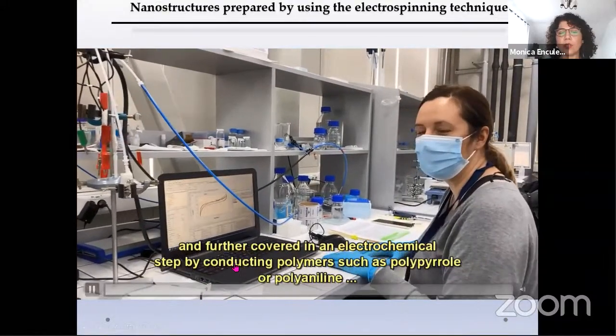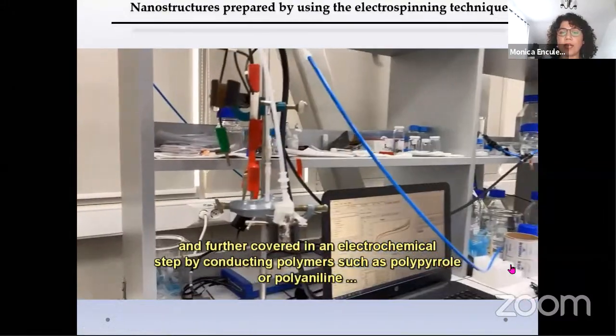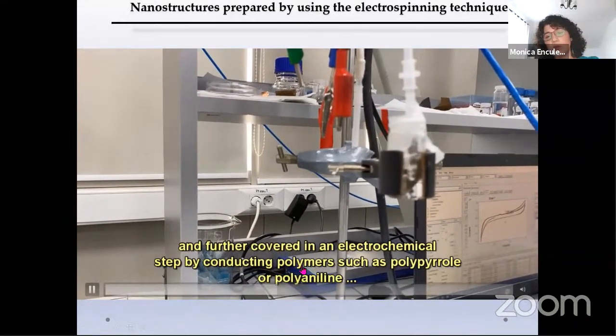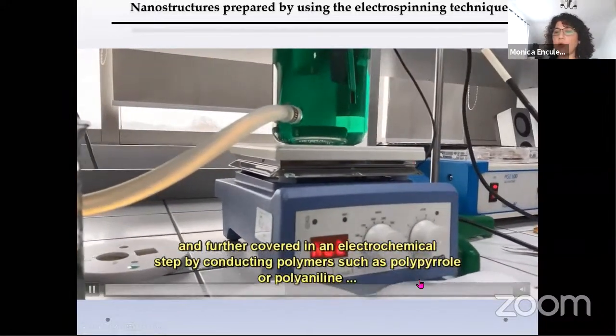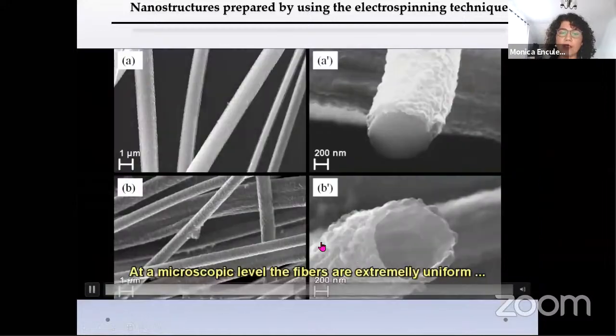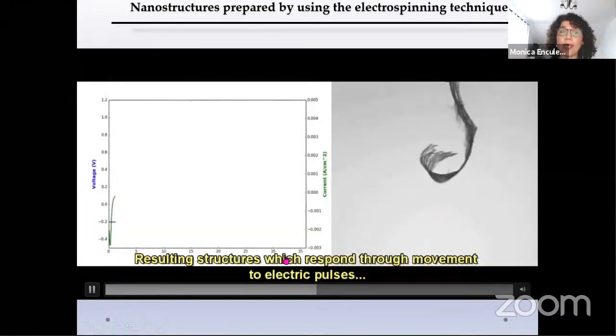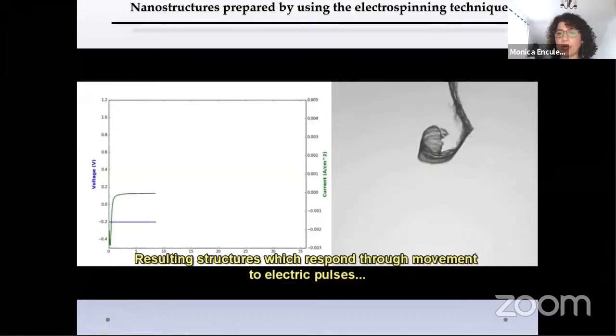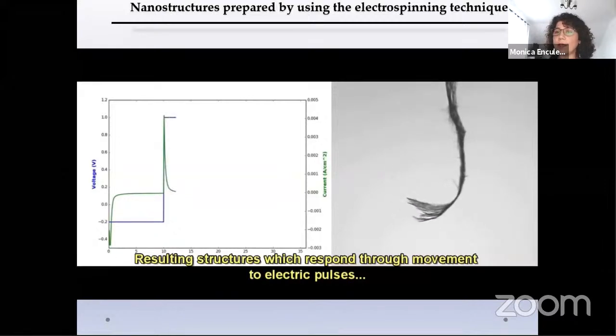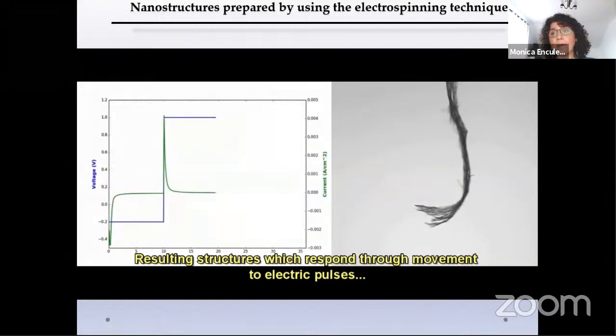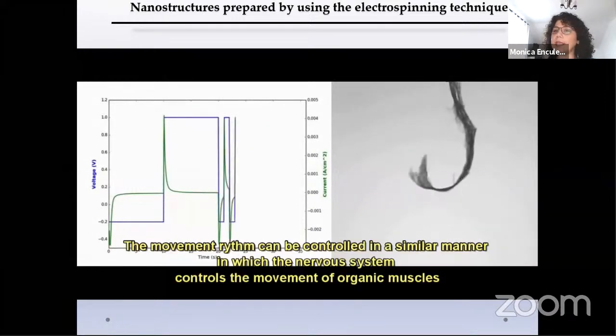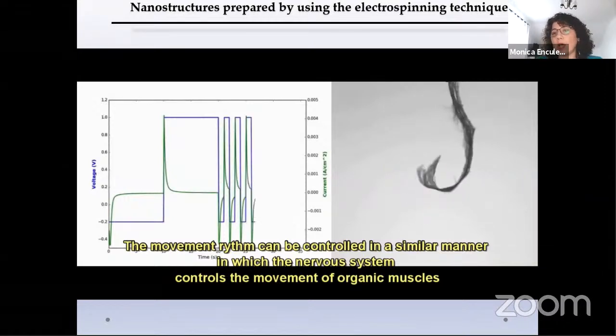And you can further cover it electrochemically with conducting polymers, polypyrrole or polyaniline, in the chemical bath. And at the microscope, you see the polymer fiber, that is the core, and the outer layer, which is the polyaniline. And this structure, if we put an electric pulse, we can make them flex. We can make them mimic the muscle. So we can make artificial muscles, and by playing with the electric voltage, we can make them flex at the rate or at the speed that we want.